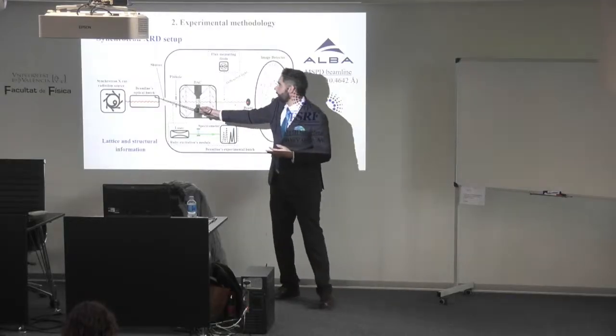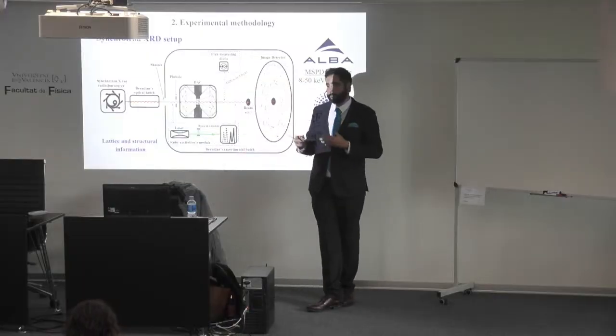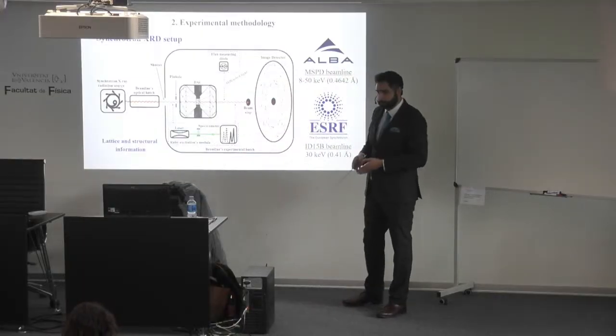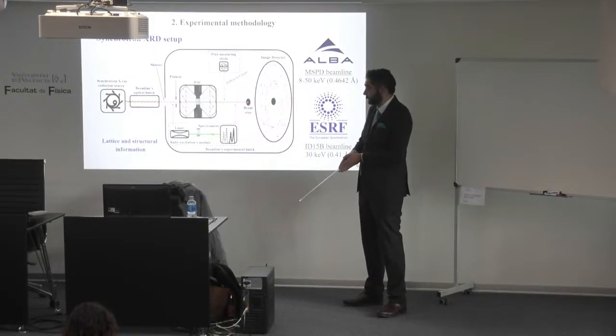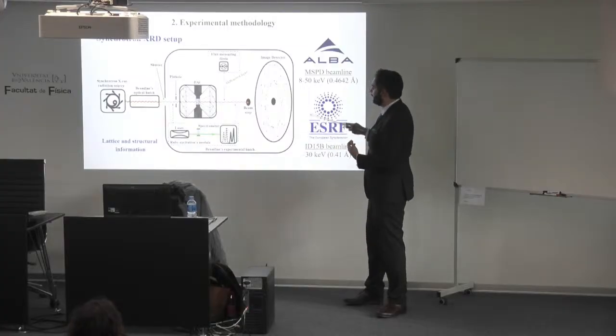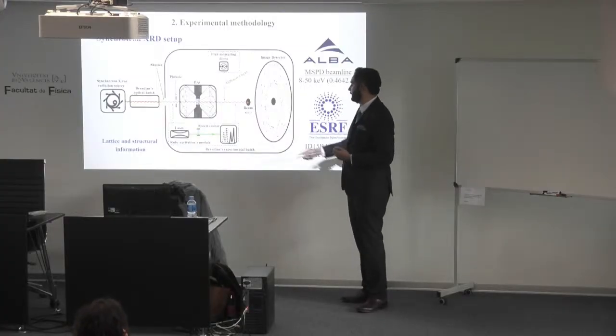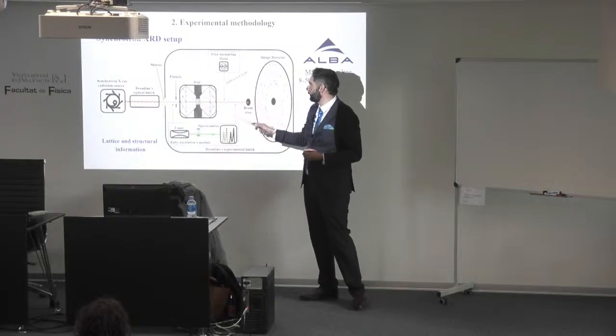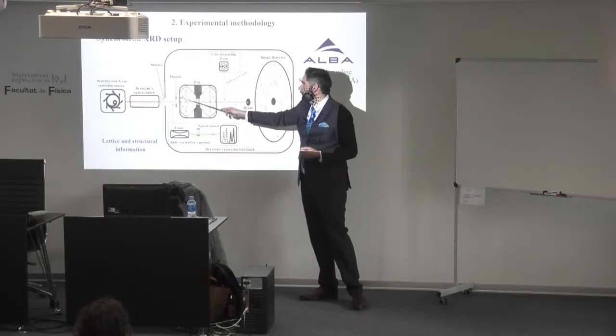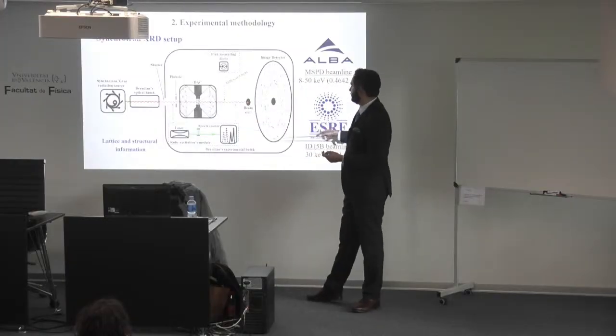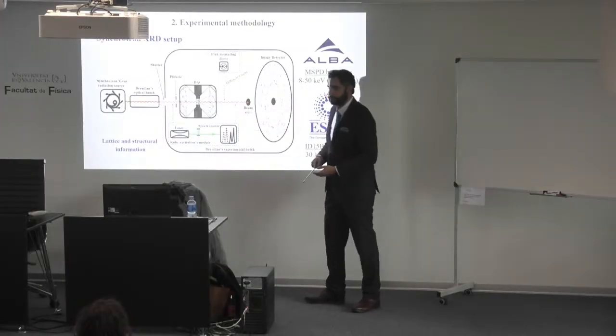Then we have an optics hutch. For an XRD, this optical hatch will need an insertion device, and it will tune the signal in order to be monochromatic with the correct shape. And then we have access to the experimental hutch, where we locate the diamond anvil cell, restrict the signal with a pinhole, and we get in the detector the diffraction of the sample.